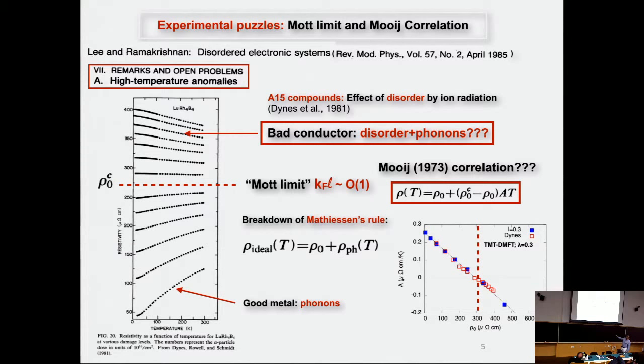Now I want to emphasize that this regime is not the regime near the metal-insulator transition, not too close, because for example, in scaling theories, you are describing curves where the resistivity is going up, but to a finite value, and that this finite value diverges, and you have a family of curves that you can scale, but all curves are going up, right? When the curves are not going up like this, this is obviously outside this critical regime.